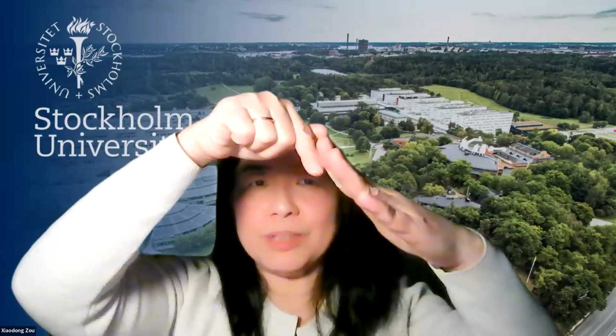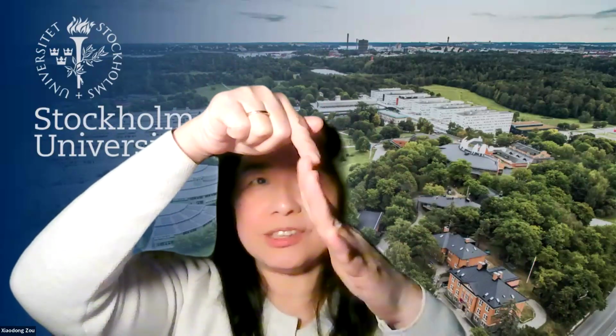And when collecting with a tilt, how often do you have to readjust the stage height to stay eucentric? And is this automated in your system? For CRED, you don't need to do any adjustment. When you actually sweep, we don't do any adjustment. The sample height stays because actually the beam is not moving. If you tilt the beam, the crystal is sliding like this, and the height is always the same. So we do not adjust the height.